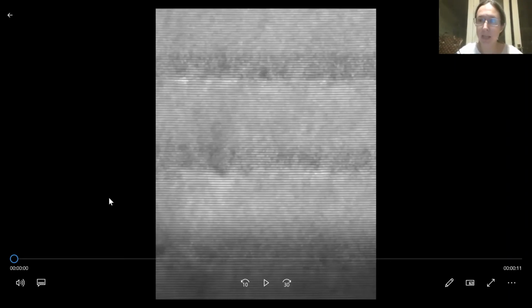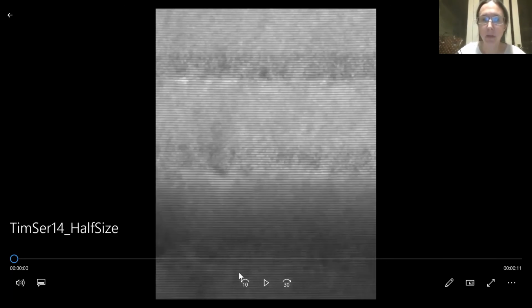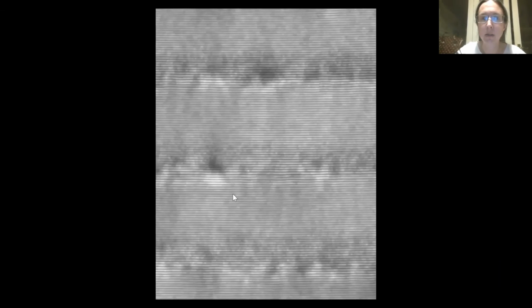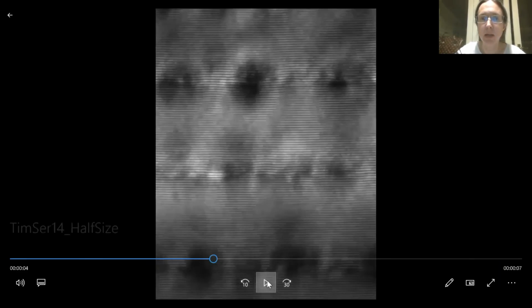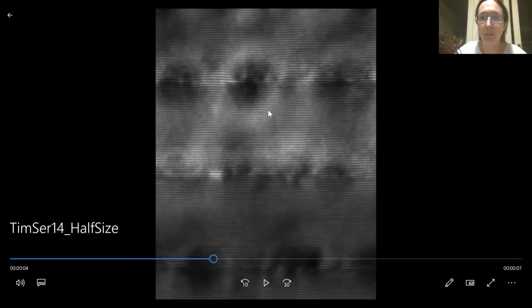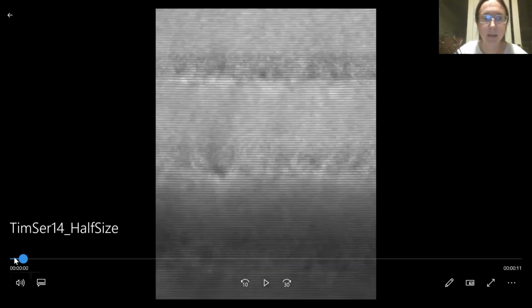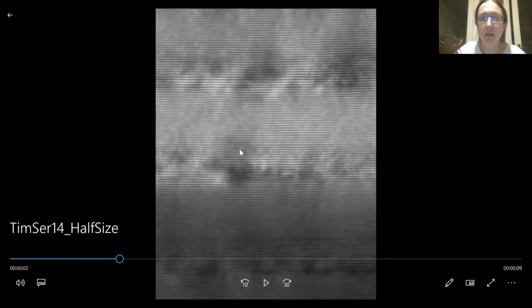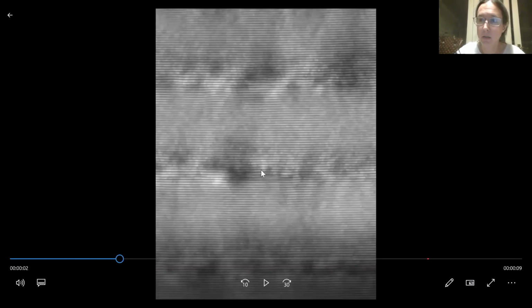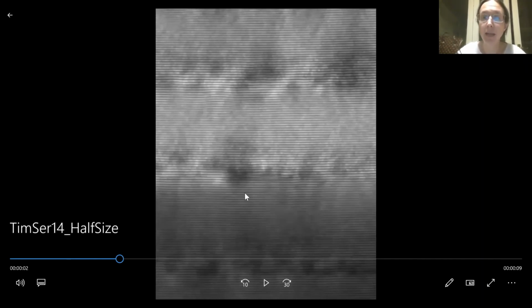So we're going to keep on taking pictures of the quantum wells in the transmission electron microscope by shining an electron beam on the sample, and watch what happens. Okay, and what you can see is as we expose those quantum wells to the electron beam, they just get more and more and more blobby. Okay, I'm going to take that back and see if I can show it to you again. So we can see with exposure, the quantum wells develop this blotchy contrast that we've seen before in the earlier TEM images. And suddenly everyone started to get very suspicious. Was the blotchy contrast really because the quantum wells varied with indium content? Or was it because the way we were taking the picture was actually changing the quantum wells?